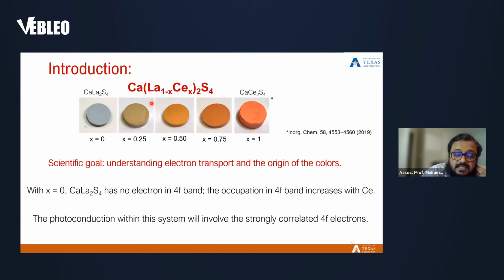This work started with calcium lanthanum sulfide. And when cerium is incorporated in calcium lanthanum sulfide, as the cerium concentration increases, we see the color of the samples changing. It's getting from gray, it's not exactly gray, it's like whitish, it's not a metallic color, to a red color. And red color we know is band gap less than 2 electron volt, would be good for catalytic materials. So the initial goal was to understand the color change and to see what kind of transport is taking place in these materials. This is how we started this work.